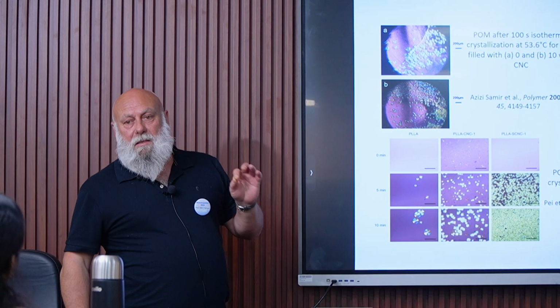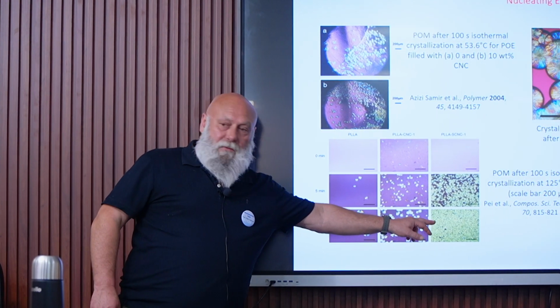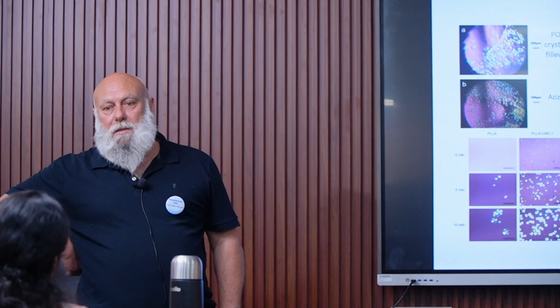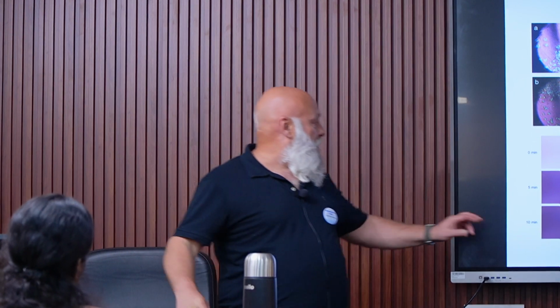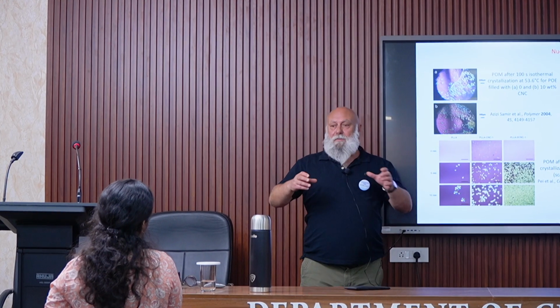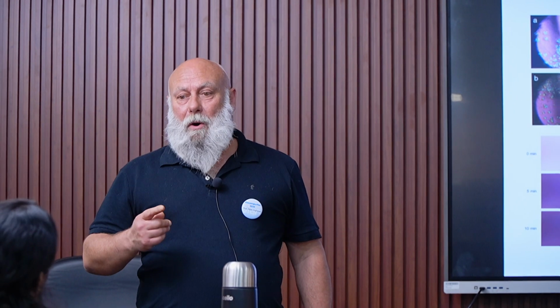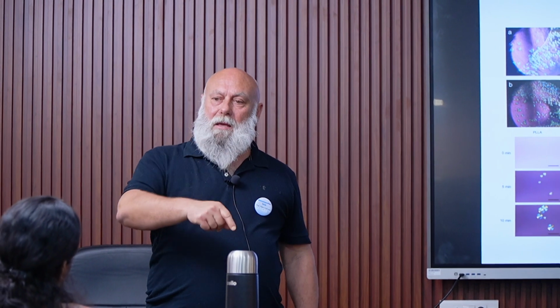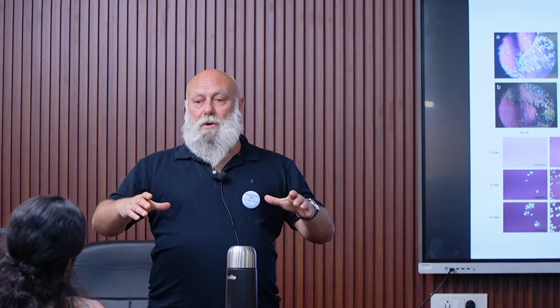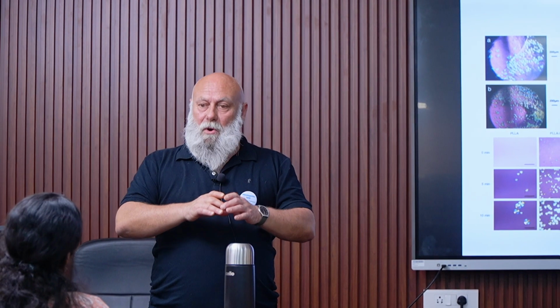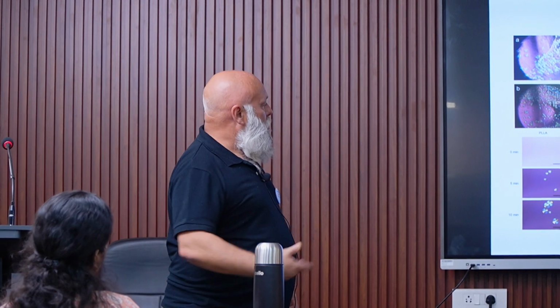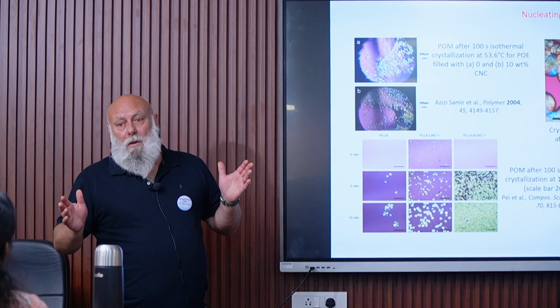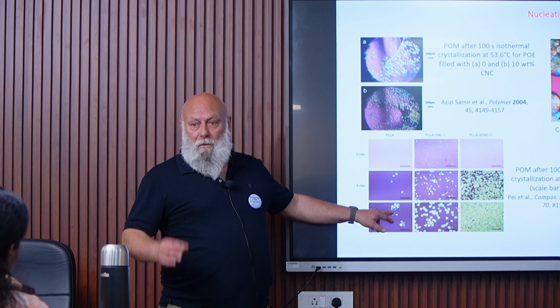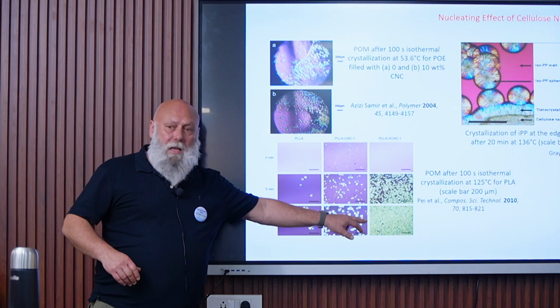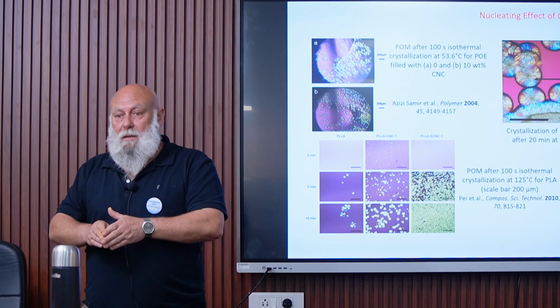If you perform DSC experiments on this sample and on this sample, which difference did you expect? You can see the difference is that here you have big crystals, here you have small crystals. So maybe the temperature of melting, the melting point, because the melting point is directly linked to the size of the crystal. When you have big crystals, the melting point is higher. When it's a small crystal, the melting point is lower. You can also check the degree of crystallinity, but it will not give too much information because you can have a few big crystals or many small crystals and the same degree of crystallinity.